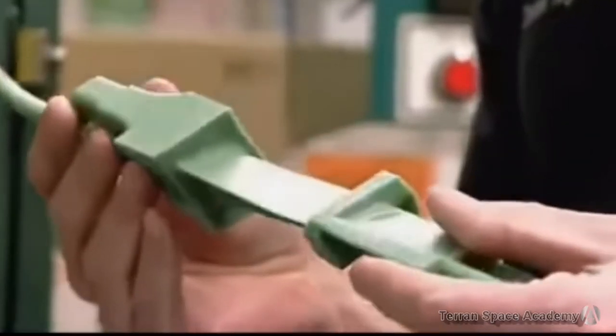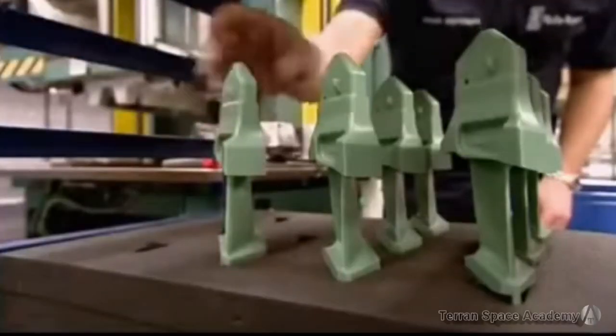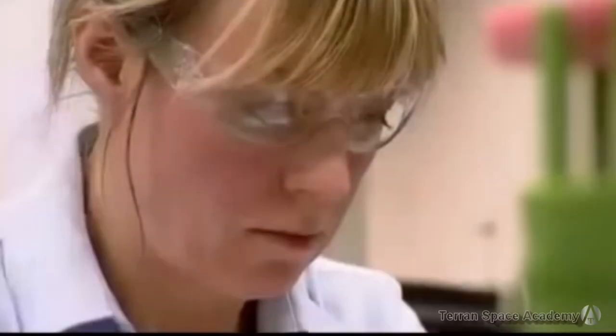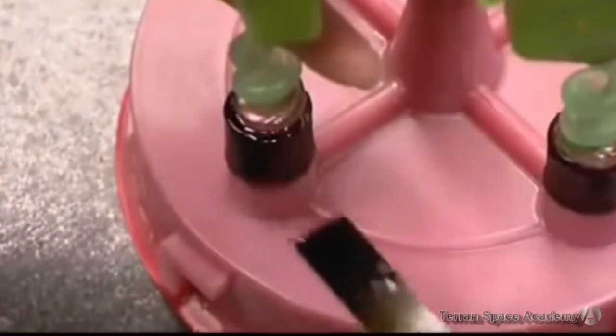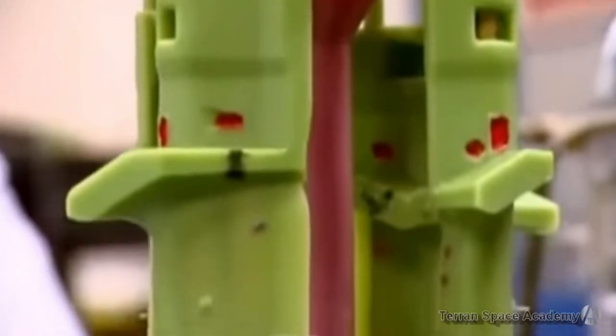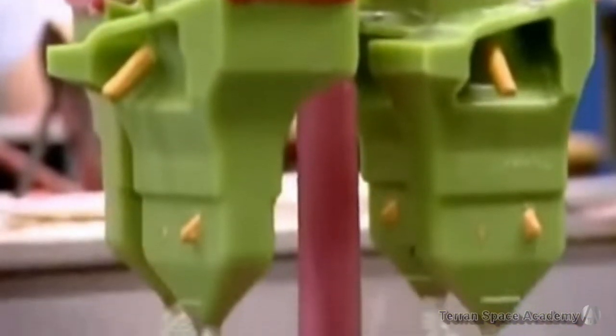They first make a ceramic core that has the internal cooling channels in place. They inject wax to form the shape of the blade. Platinum pins are inserted to support the core inside the wax. Then the form is coated with a mixture of aluminum silicate to form a ceramic coat. Several more coats are applied and then the wax is melted out, leaving room for the alloy.